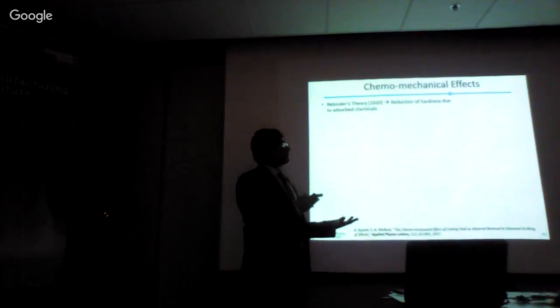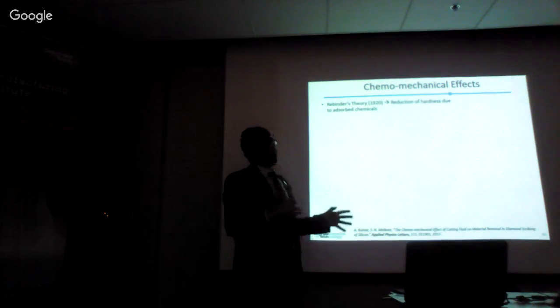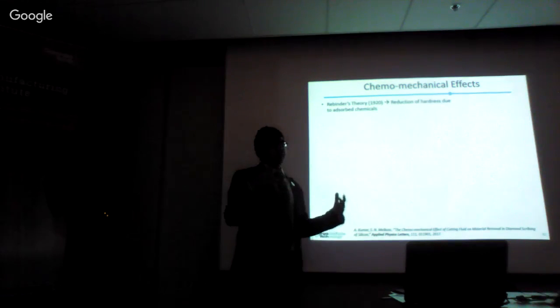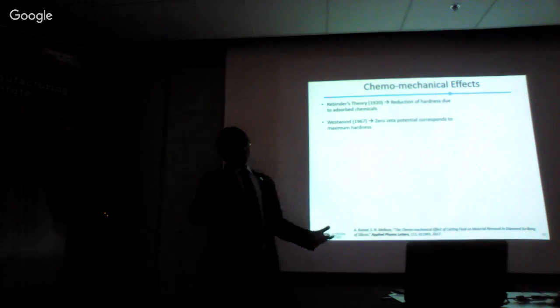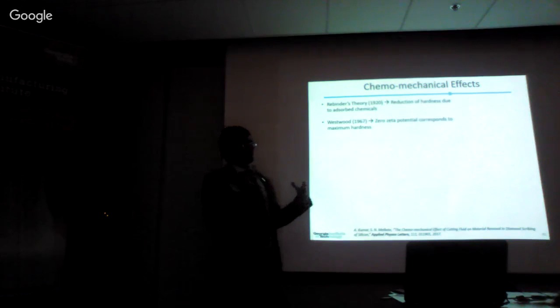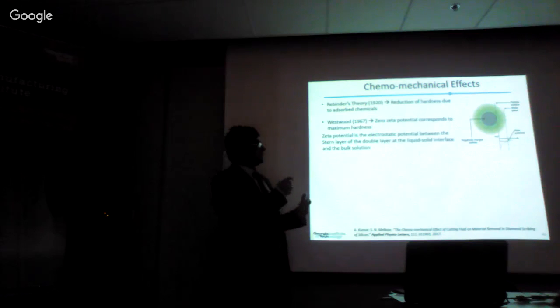To explain our findings, we take help of an effect called Rebinder's effect, which was found way back in the 1920s, where they found that there's a reduction in hardness of rocks due to the adsorbed chemicals. This was revisited by Westwood in around the 1960s, who correlated the zeta potential of the liquid in contact to maximum hardness. Zeta potential, to note, is the electrostatic potential difference between the stern layer of liquid in contact with the solid and the bulk liquid solution.